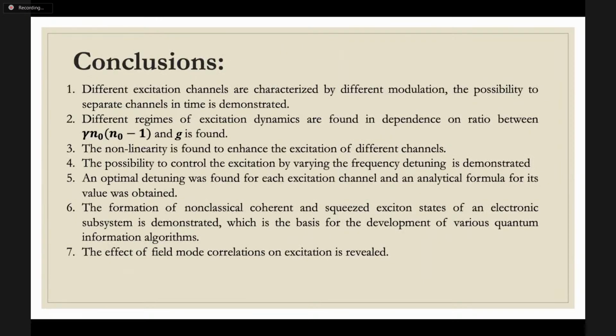And finally, I come to the results, and I will summarize them. First, the different excitation channels are characterized by different modulation, and the possibility to separate channels in time is demonstrated. Then different regimes of excitation dynamics are found in dependence on the ratio between the nonlinearity and the parameter G, which compares the strength of the interaction of field and field with the electronic subsystem. And next, the nonlinearity is found to enhance the excitation of different channels.